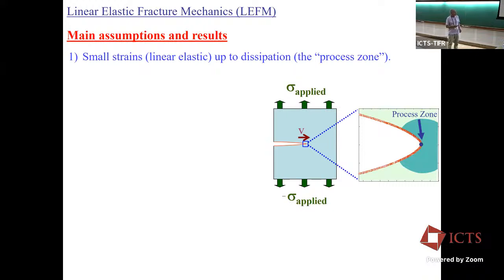So the main assumptions are that we're talking about small strains. That's where the linear elastic part comes in from linear elastic fracture mechanics. So the strains in the material are all very small. And there's an assumption that the strains are small up to where dissipation takes place at the tip of the crack. In fact, the only place where energy is dissipated in this system is where material is broken at the crack tip. So everywhere around it, life is conservative. And all of the stuff that we really don't understand, the proverbial rug under which we sweep all the stuff that we don't know, is contained very near this singularity.